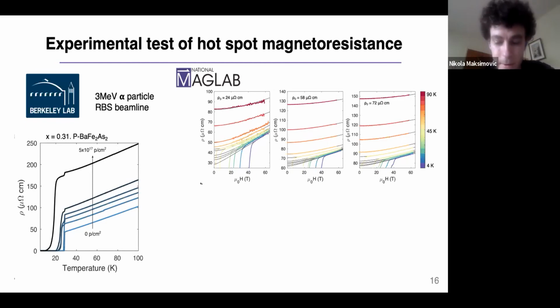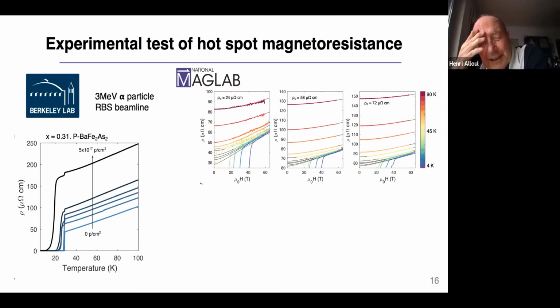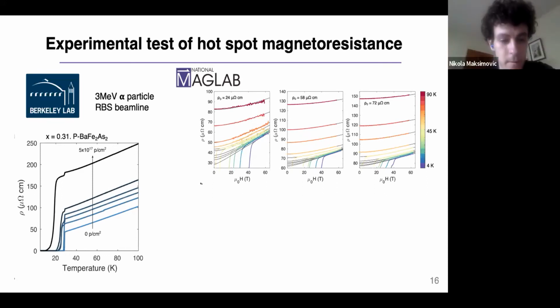You're correct. We have done very careful work on cobalt-122 with Florence Rullier-Albenque, in which we tried to analyze the transport in terms of two bands and two different scattering rates, showing that they were very similar. In fact, in that case we find a T-squared term and not even a T-linear one. Here, all this is done as if it is a single band.